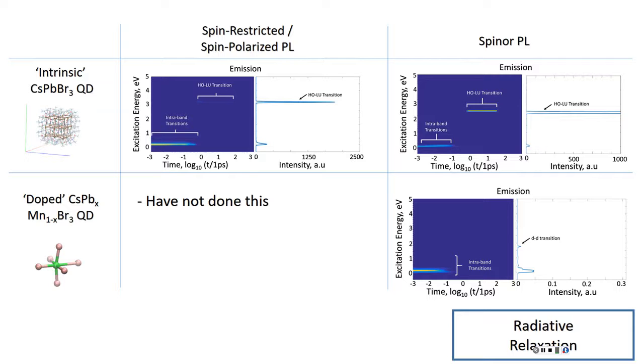A couple of questions. Your intrinsic spin polarized time-dependent luminescence, and you have a bracket telling the HOMO-LUMO transition. Is it possible to zoom in into the vicinity of this transition? Not right now, but in the future, to zoom in energy from maybe 2.9 to 3.5, and in time from maybe 1 picosecond to 10 picoseconds, because right now it is almost invisible to the human eye, to show that this feature does exist. Just make it as an inset? Yes, inset, to sound convincing for a reader. It was not a question, it was a comment.